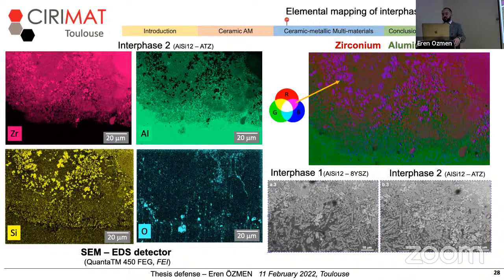And when I stack these images, I see that some purple areas, which is a mixture of red and blue, which is the mixture of zirconium and silicon, appear in the microstructure. So that was very interesting to see because zirconium is coming from the ceramic and this silicon is coming from the metal. So for me, that was the first indication that a chemical interaction is occurring between the ceramic and metallic part, by 2 different elements existing in the same area.